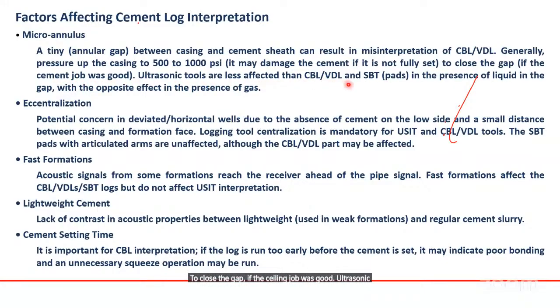Ultrasonic tools are less affected than CBL, VDL, and SBT, but in the presence of liquid in the gap, with the opposite effect in the presence of gas. Eccentralization: potential concern in deviated and horizontal wells due to absence of cement on the low side and the small distance between casing and the formation. Logging tool centralization is mandatory for USIT and CBL VDL. The SBT pads with articulated arm are unaffected, also CBL VDL. Fast formation: acoustic signal from some formations reaches the receiver ahead of the pipe signal. Fast formation affects the CBL, VDL, SBT logs, but doesn't affect USIT interpretation.